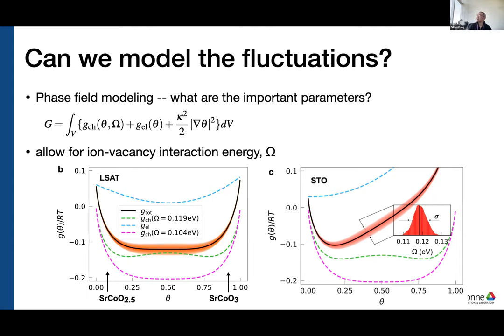values for omega's 0.119 eV, that is the ion vacancy interaction energy. So that is essentially describing how much it wants to turn into the Brownmillerite phase, where you have ordered oxygen vacancies. And the purple dashed line shows also the chemical component, but with a different interaction energy. So what we're trying to highlight here is that the total energy, which is in black, can be very flat when you choose the right levels of this omega interaction energy. And so we picked the one that was at 0.119 eV.